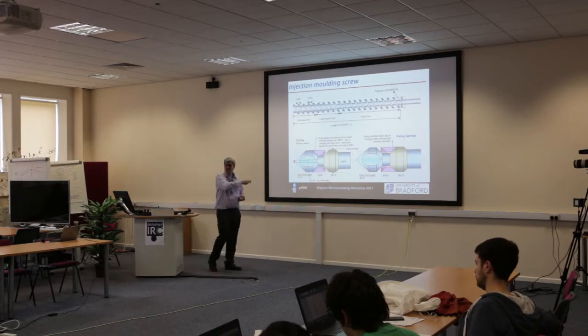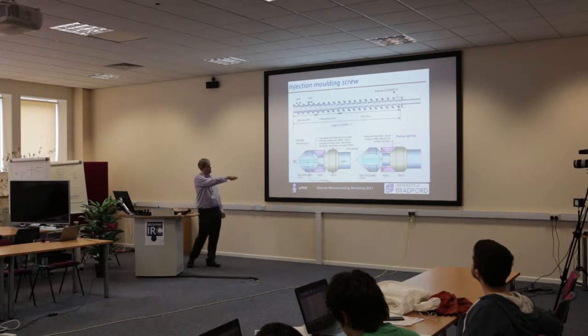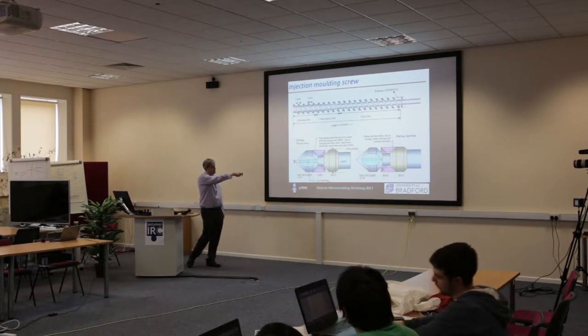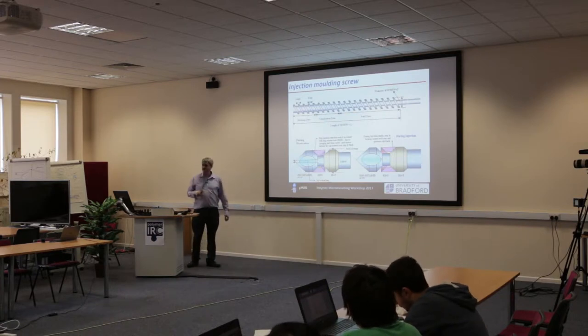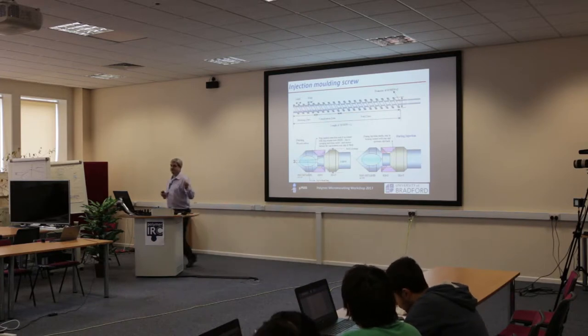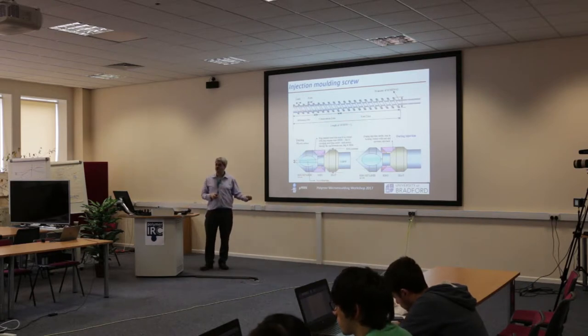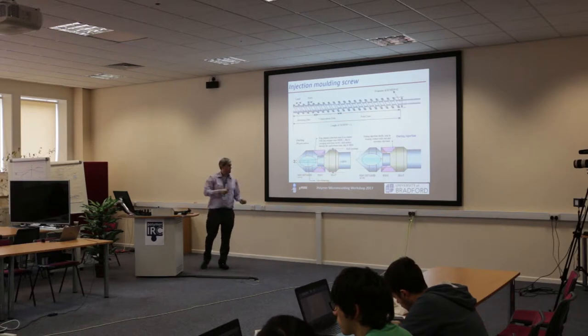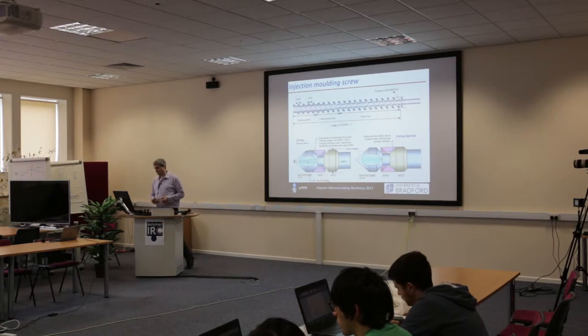The problem for micro injection molding is that when trying to inject with really high precision, the movement of this check ring backwards gives a slight lack of control over the volume of material in that area. That unknown volume can in many cases be equivalent in size to a considerable number of the parts you're trying to manufacture with micro injection molding, introducing a slight unknown in your dosing and injection capability.